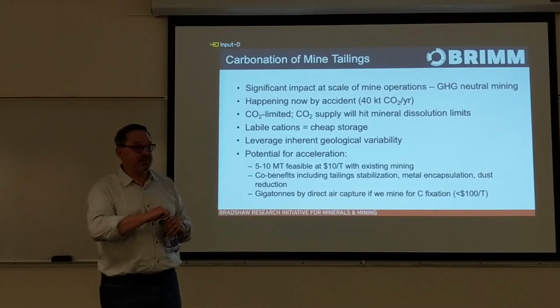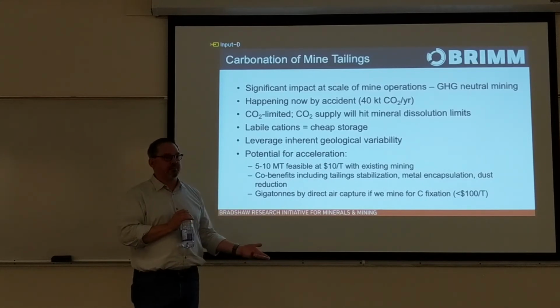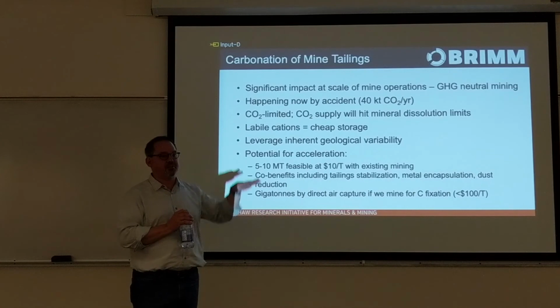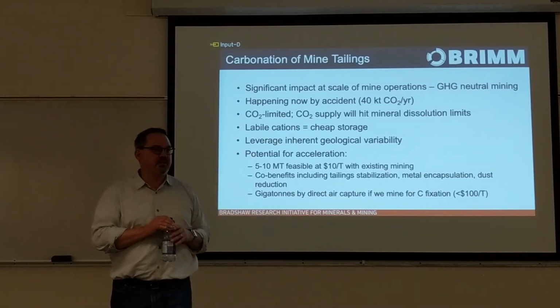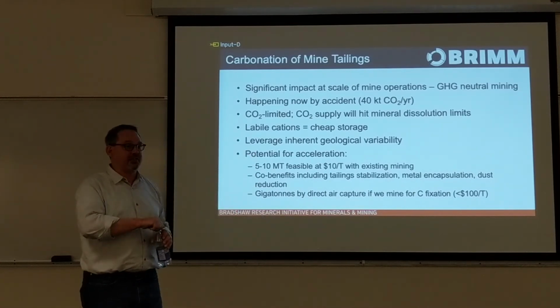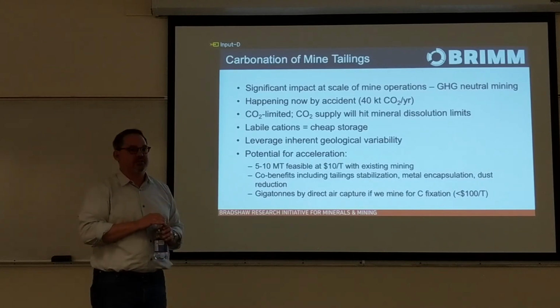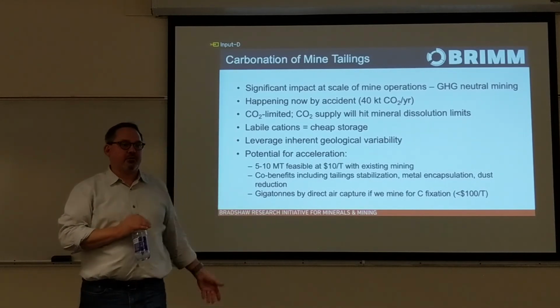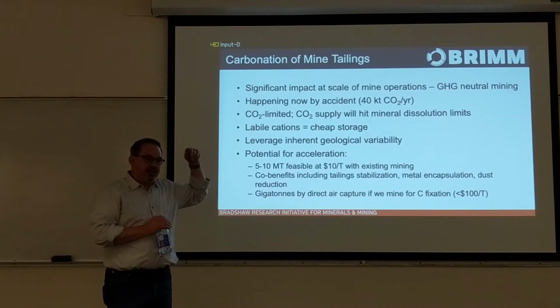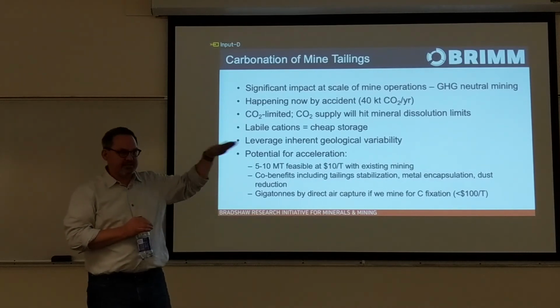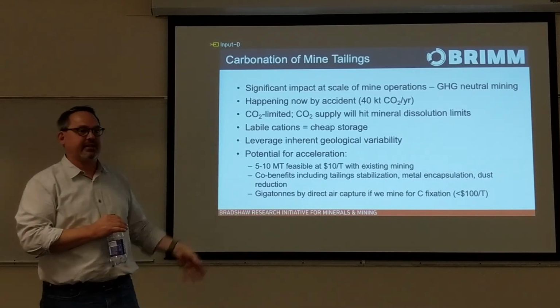So we measured the carbonation rate. The whole experiment ran on its balance. So we could actually measure the carbonation rate by watching the weight of the column increase over the 100 hours and adding enough CO2 that the mass of the column is increasing. But we also measure the CO2 flux because we know the gas flux in. And then we measured the carbonate abundance in the minerals all through the material at the end.